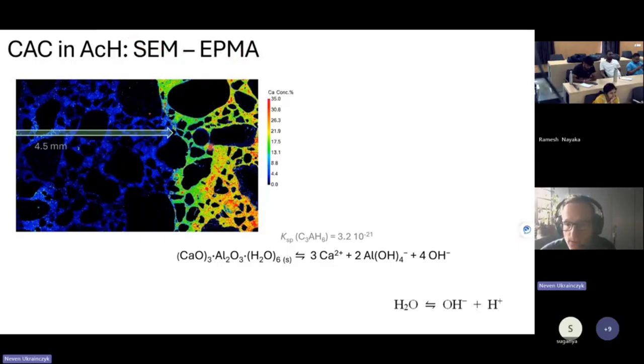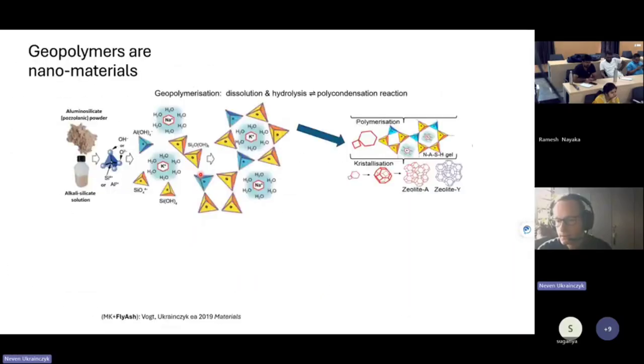Here, for each pixel, you can get a very good signal. But in EDS, in normal SEM, there is not enough energy, or you need a very long measurement time, which is not possible because the image drifts. So either you need a very advanced technique, a very high energy field emission gun, and then you can really get chemical composition per pixel. But this is a rare technique. Not many labs have this.